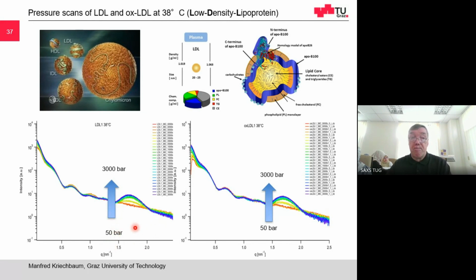So this is done at 38 degrees, and this is also done at 38 degrees. We start out at 1 bar or 50 bar, and we go up to 3,000 bar. We see mainly two changes. Here in that range, in the inner part of this scattering curve, this range corresponds to the lipid core. So this change is caused by the lipid core, and the inner part is caused by the protein which surrounds this lipid core.